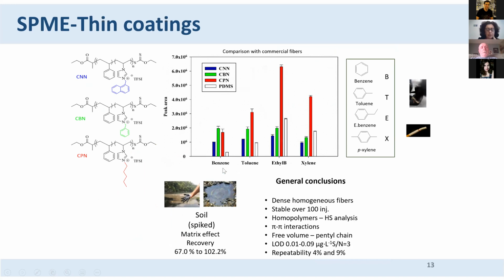And we used the well-known mixture BTEX, benzene, toluene, ethylbenzene, and xylene, to test the fiber. And as you can see here, we could get some selectivity. So we could extract very well the ethylbenzene with the fiber that had a long side chain. And in particular, this was a very nice fiber for all the other compounds. Realize that this time the commercial fiber was PDMS, and it is here. So we are doing much better than the commercial fiber. Repeatability here is quite good.